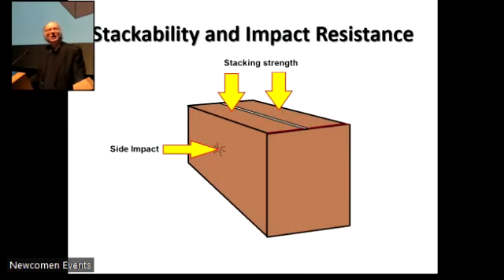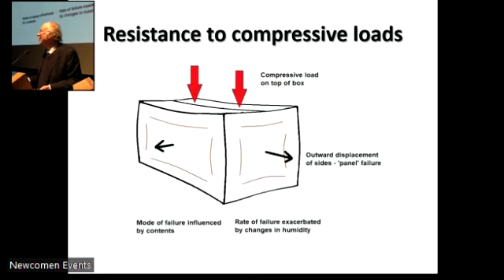And what we're interested in is stackability, the stacking strength, and to a degree side impact, which can arise not only from external forces, but also from the actual movement of the contents within the box under vibration. And what tends to happen if you squash a box, you get this characteristic panel failure, where these panels are pushed out at the side, the top bends towards the middle, and the corners, which are the strongest, are the last to fail.